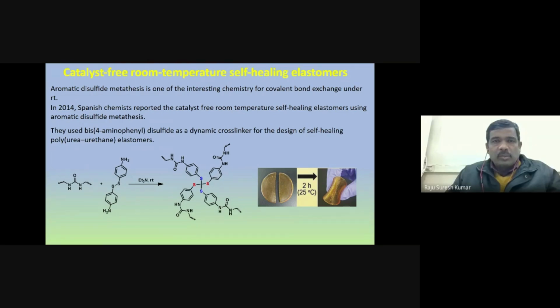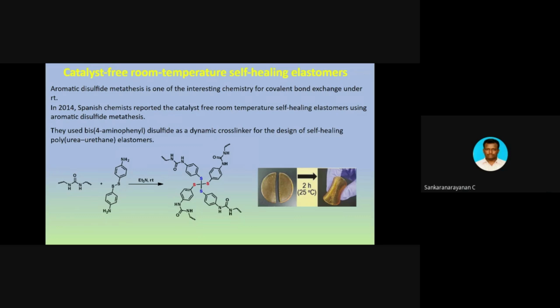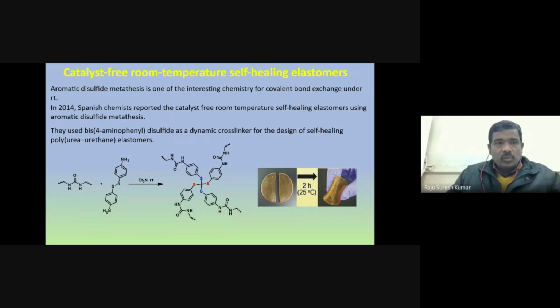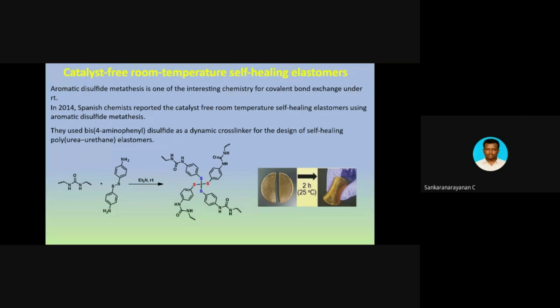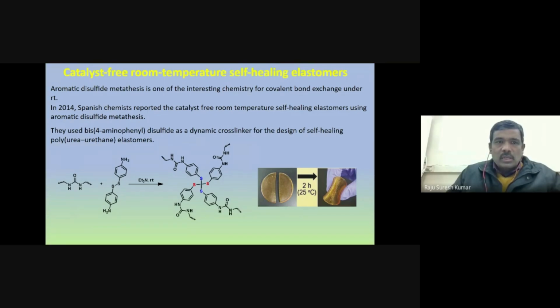Catalyst-free room temperature self-healing polymers were recently invented. What we discussed previously are self-healing products that may happen under external stimulation. But here in 2014, a Spanish research group discovered a catalyst-free self-healing product, which belongs to the disulfide exchange reactions. Self-healing polymers that can spontaneously achieve quantitative healing in the absence of catalyst had never been reported. So this is the first report. They used aromatic disulfide metathesis to synthesize this product.